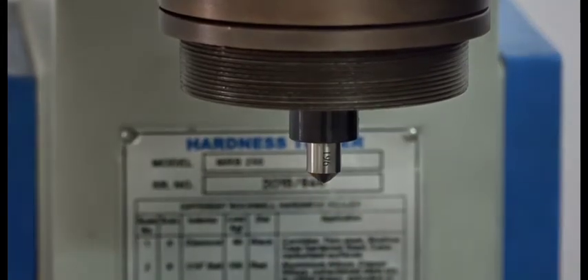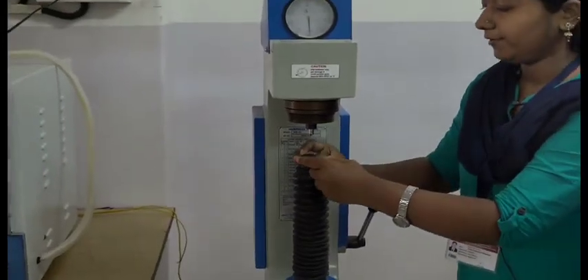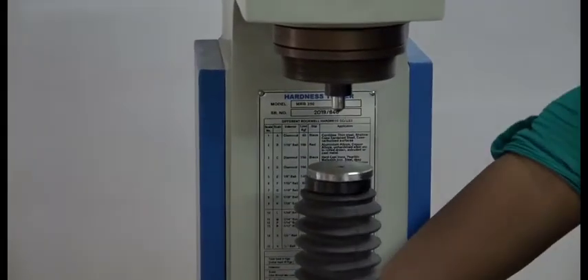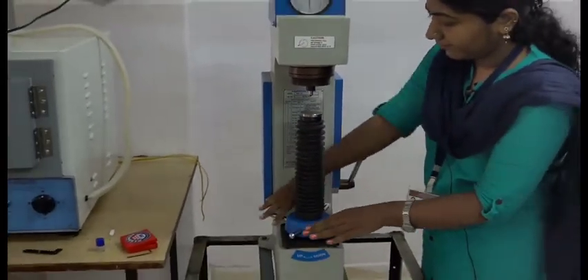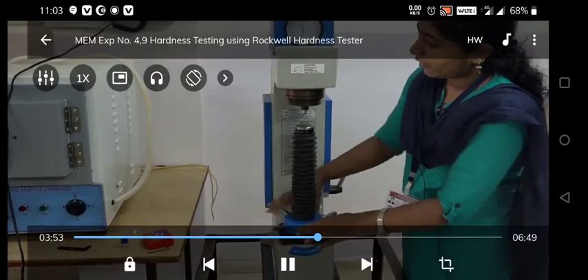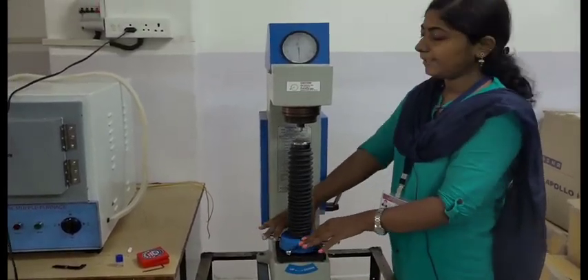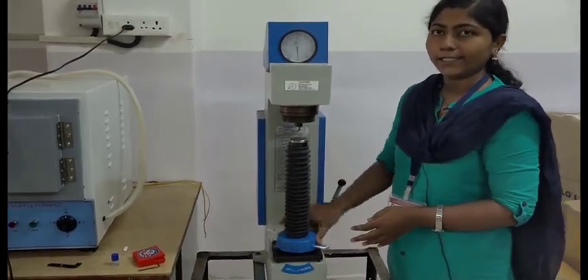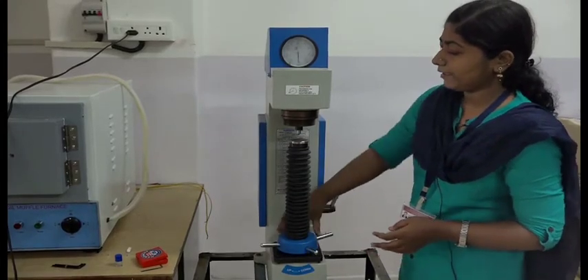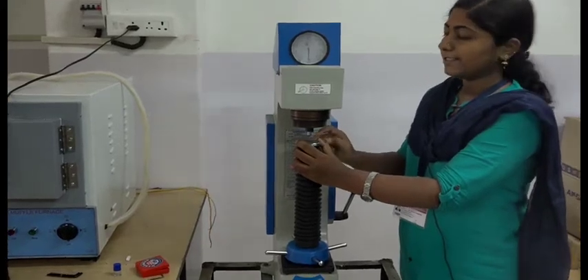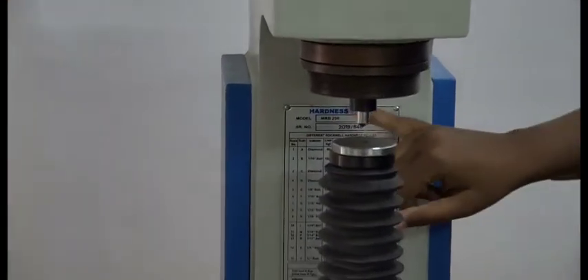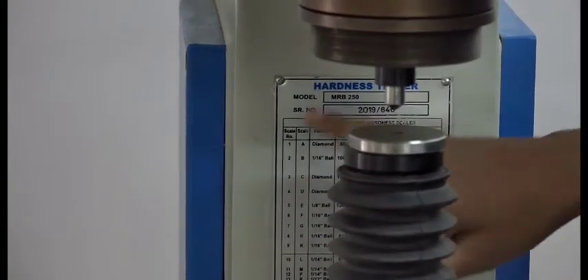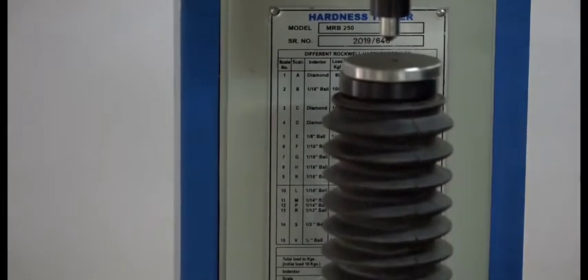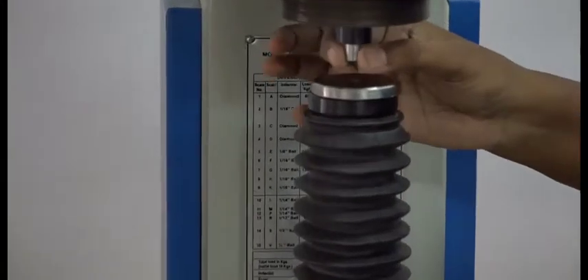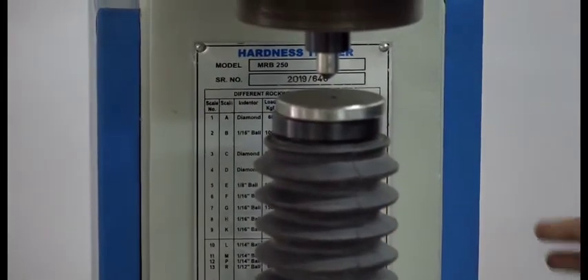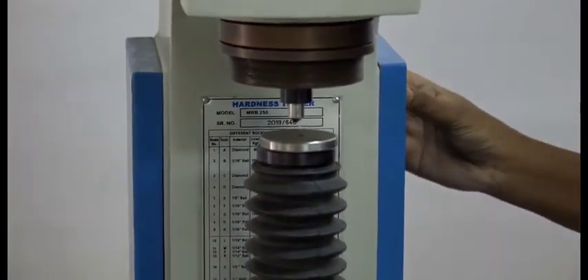We put our specimen here, and with the help of the key, the diamond indenter is fixed. Now the specimen is put here. With the help of the hand wheel, we rotate it and move it up and down. There are always two types of load, major load and minor load. The minor load of 10 kg is always fixed. As our specimen is a standard steel specimen and the material is hard metal, a scale chart is available here. So we select scale C, the indenter is diamond, and a load of 150 kgf is selected on the load selector.